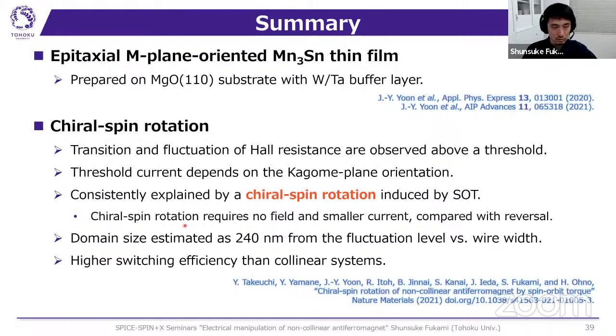And the chiral spin rotation requires no field and a smaller current compared with the chiral spin reversal. The domain size was estimated as 240 nanometers from the fluctuation level versus the wire width. And I also described that the chiral spin rotation shows a higher switching efficiency than the collinear systems. Okay, that's all. Thank you for your attention.